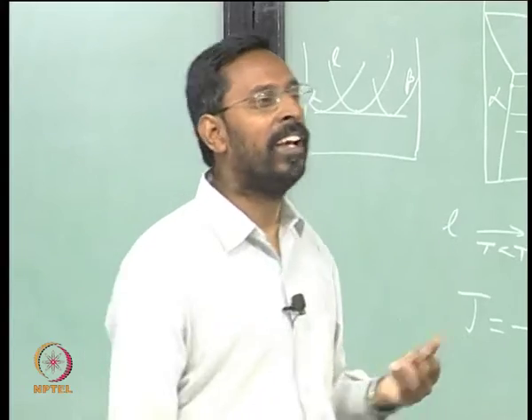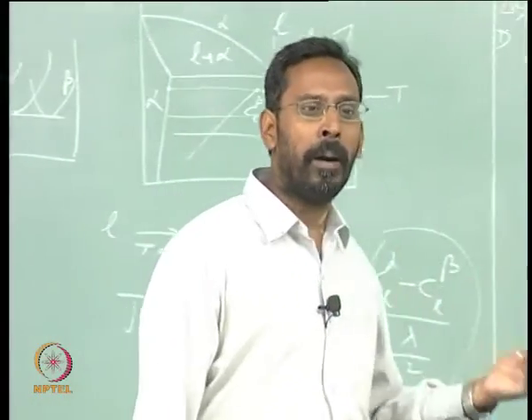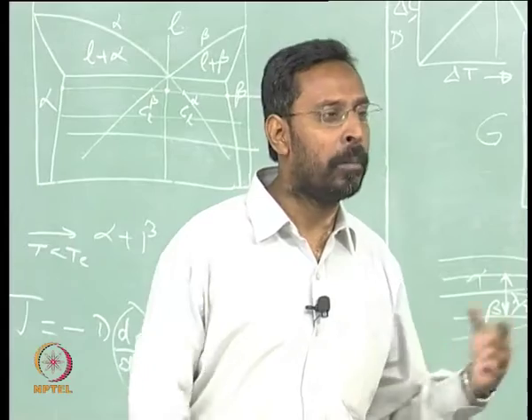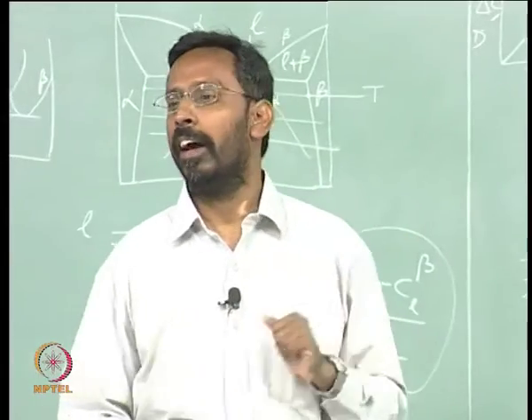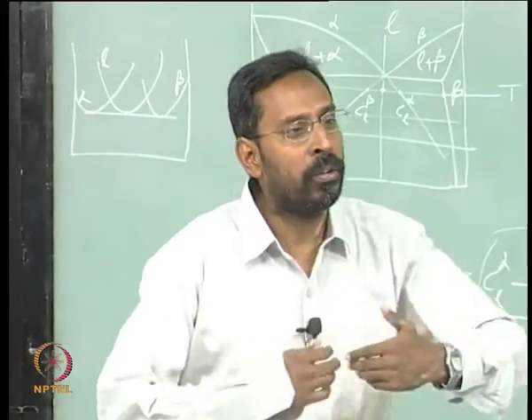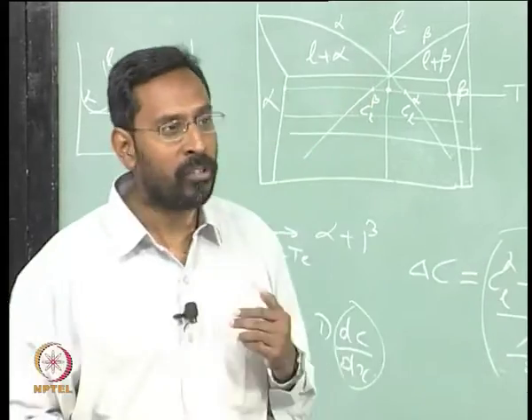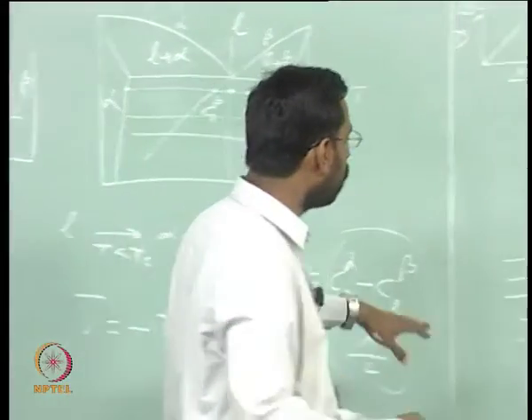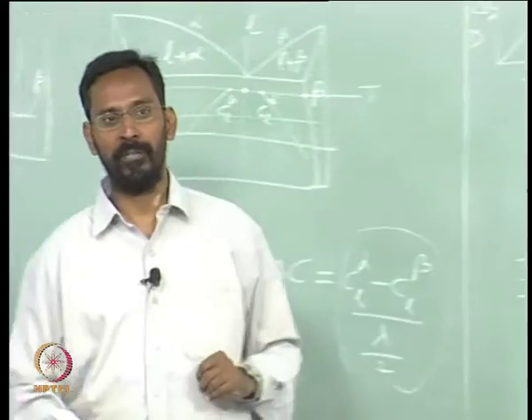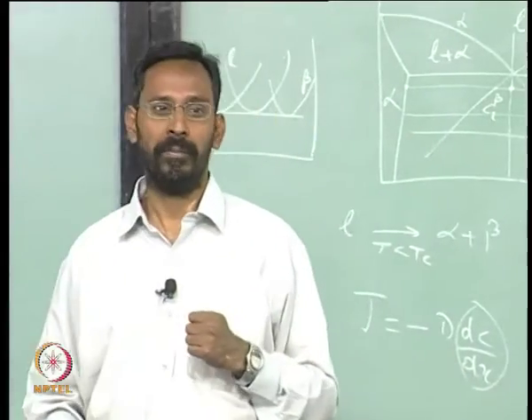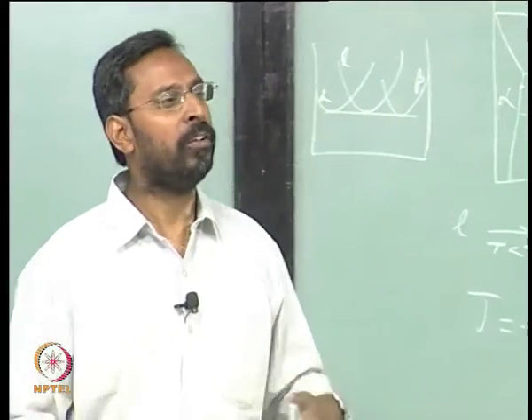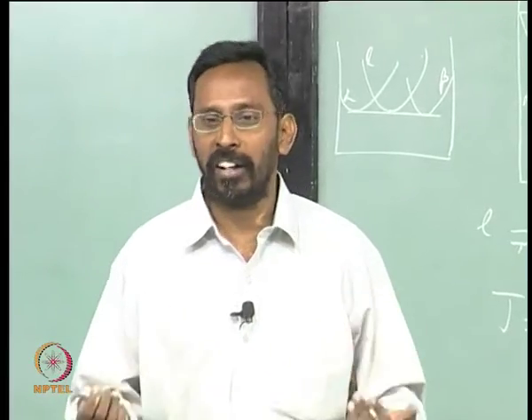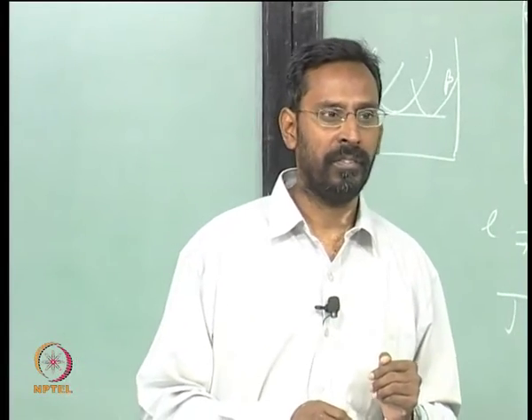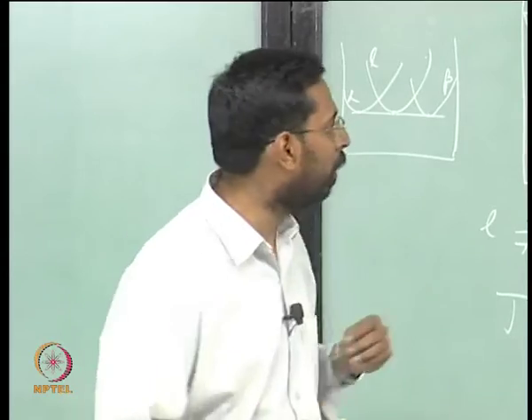That is the reason why for any eutectic mixture, if I pour the liquid metal into a metallic mold versus a sand mold, you would see the growth rates are different. In fact, not only growth rates, the lambda is also different. You get a finer lambda because the nucleation rate is higher and the R star is smaller, so all those things become important.